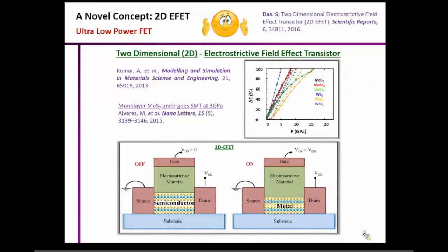And this is exactly what we proposed earlier using this two-dimensional electrostrictive field effect transistor, where instead of a normal dielectric, we replace this normal dielectric in the gate stack by an electrostrictive or piezoelectric material. To give you a layman's understanding: when you apply a gate bias, this piezoelectric material goes through expansion, and that introduces an out-of-plane strain on the 2D material, and as I articulated, this out-of-plane strain then reduces the band gap of the 2D material, and it could convert this 2D material from semiconductor to metal.